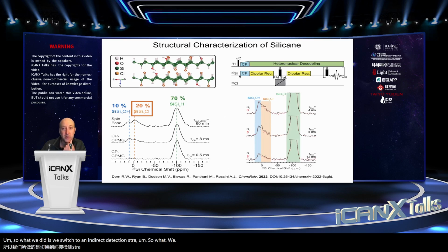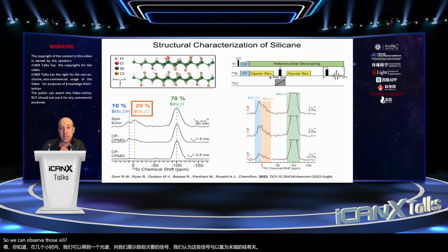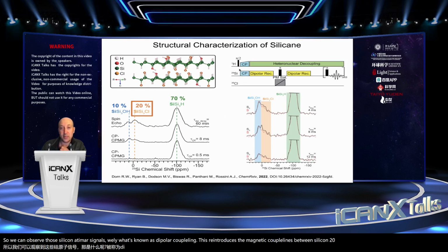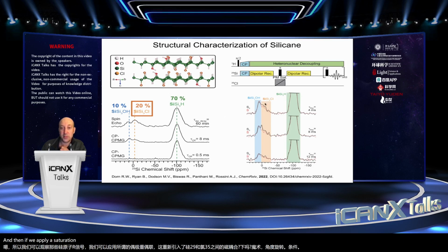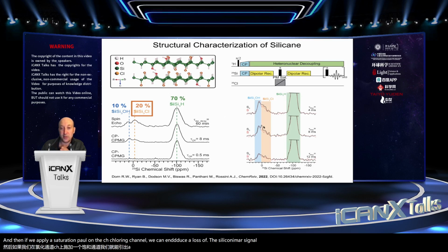So what we can do is observe the silicon-29 NMR signals, and within a couple hours, we can get a spectrum that shows us those minor NMR signals that we think are associated with silicons that are chlorine terminated. So we can observe those silicon NMR signals. We can apply what's known as dipolar recoupling. This reintroduces the magnetic couplings between silicon-29 and chlorine-35 under magic angle spinning conditions. And then if we apply a saturation pulse on the chlorine channel, we can induce a loss of the silicon NMR signal for those silicons that are attached or nearby to a chlorine atom.